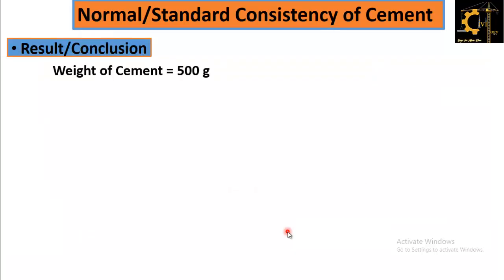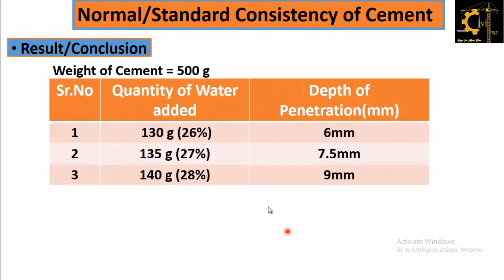Now coming towards the conclusion, the weight of the cement for this experiment is 500 gram. Let's suppose in serial trial number 1, we took 26% of 500 gram, that is 130 gram of water. The depth of penetration we obtained was 6 millimeters, which is lower than our range. In the second trial, we took 27% by increasing 1% of water. It comes out to be 135 gram, and the penetration was 7.5 millimeters. When we increased the percentage of water to 28%, which comes out to be 140 gram of 500 gram, the penetration came to 9 millimeters. Okay, now this is within the range.